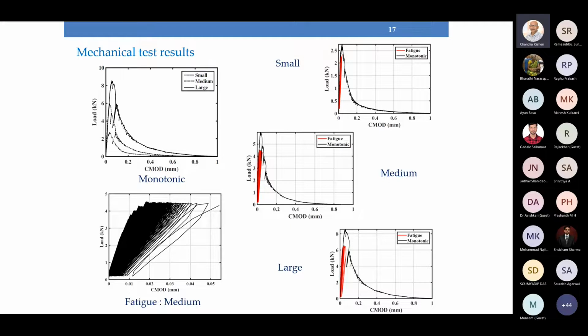Under fatigue, this was performed under load control. These are the results for a 2 Hz frequency. This is the load versus CMOD response, and we see that with increasing number of cycles of loading, there is a gradual decrease in the slope of this load CMOD curve. The slope gives us the stiffness, which means there is a gradual degradation in the stiffness taking place.